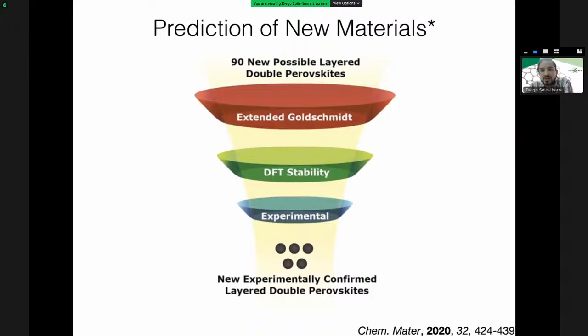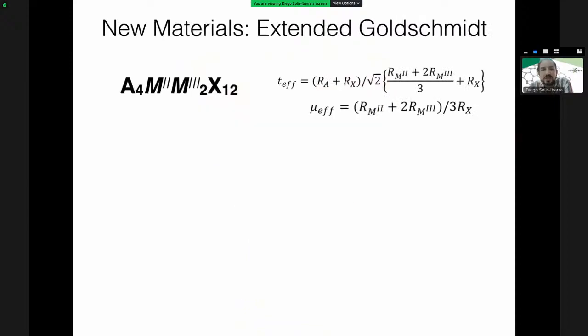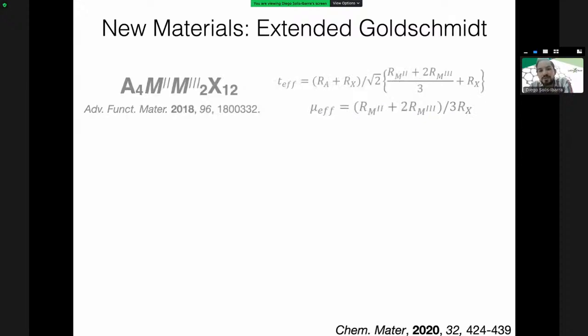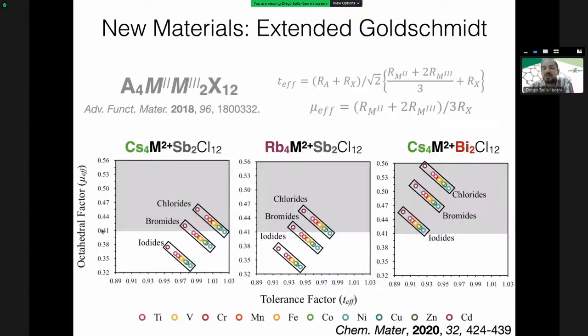So what Raul figured out is that we could do a combination of an experimental and a computational approach to reduce our space and try to see if we can find new materials. First, we did what we call an extended Goldschmidt study, in which, by considering the radius of the different elements, we can discern which ones are more likely to be stable. So pretty much we could see that the ones in the shaded or the gray area are the ones that should be stable according to this criteria. So now we're starting to reduce our search.